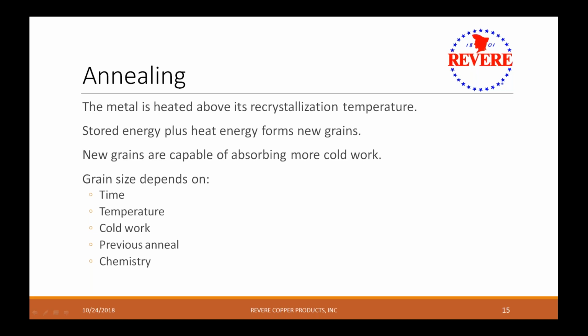So you anneal it. So let's say I gave that example of a 1/2 inch down to a 1/4 inch. Well, let's say your metal starts at a 1/2 inch, but you want to order it at 0.01 gauge. You might not be able to roll it from a 1/2 inch down to 0.01. It would get too hard. So you have to have a reset at some point in there, which is what annealing does.